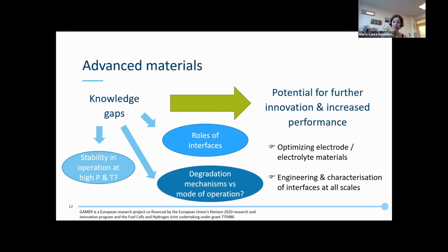Well, actually, we have done some stability tests. We remember that we are working between 400 and 600 degrees, in our case. So we are in the lower temperature regime. In our case, we have not seen pressure having a negative impact, as I showed you. The performance has been better because we are increasing hydration properties. We are forcing steam inside our material, which is the benefit. But we are also improving gas phase interaction, so kinetics have also been better.